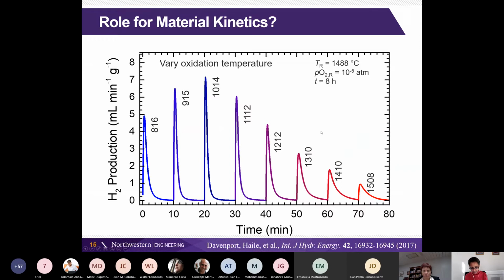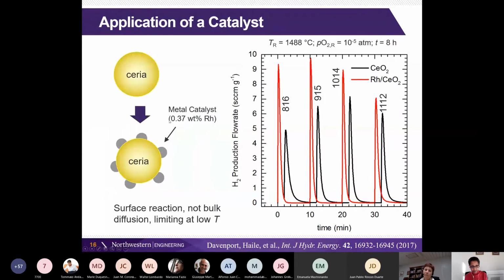If we are doing this oxidation at a lower temperature, so here's how we're changing the oxidation temperature. At high temperature, this is thermodynamically driven. So the driving force gets smaller and smaller as we go to high temperature, so the hydrogen release gets smaller and smaller. And as we go to lower and lower temperatures, eventually some sort of kinetic factor takes over, because thermodynamics would dictate that this should just continue going up and then plateau at around 700 or so. But we see that it decreases, and that's because there's a kinetic limitation. And that kinetic limitation we know is due to a surface reaction step, because if we put a catalyst material on top of our ceria particles, our monolith, we can increase the rate significantly. So where it was starting to decline without a catalyst because of the surface reaction step, when we have that catalyst material on here, we recover a very high rate of hydrogen production.